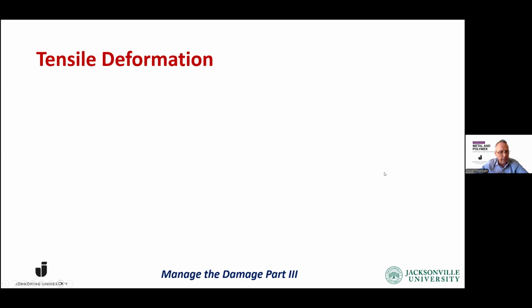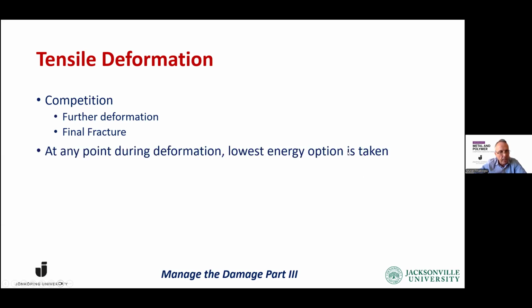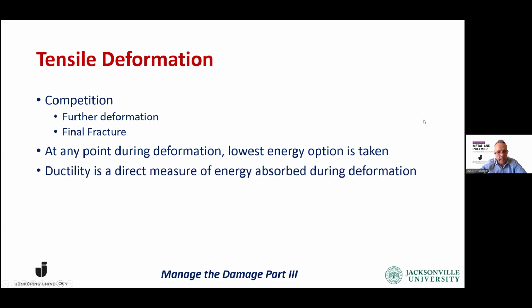Essentials of tensile deformation: it's always a competition between further deformation and final fracture. At any stress-strain combination during deformation, the lowest energy option is taken. If it takes lower energy for further deformation, the material is going to choose to deform, whereas if the energy is lower for final fracture, the fracture will take place. So ductility is a direct measure of the energy absorbed during deformation.